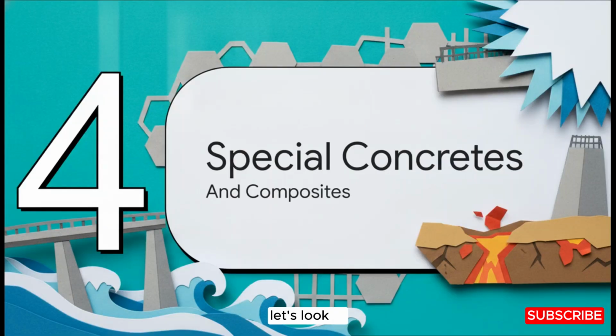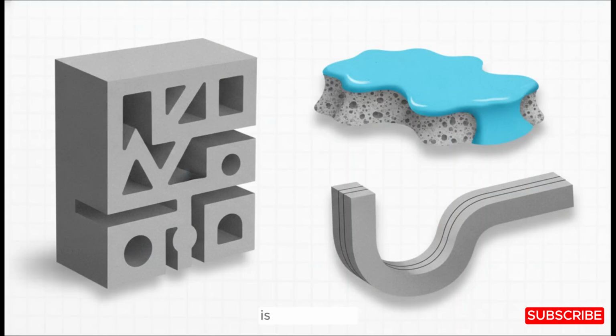All right, let's look at Section 4, Special Concretes and Composites. Concrete is pretty much the ultimate chameleon material. For nuclear radiation shielding, we create high-density concrete using heavy iron aggregates, which brings the weight up to a massive 5,280 kilograms per cubic meter. For ultra-high strength, we impregnate the tiny pores of the concrete with monomers to create polymer concrete. We even use three-dimensional basalt fibers to vastly increase the material's ductility, meaning it's actually going to bend and flex under pressure rather than suddenly snapping.